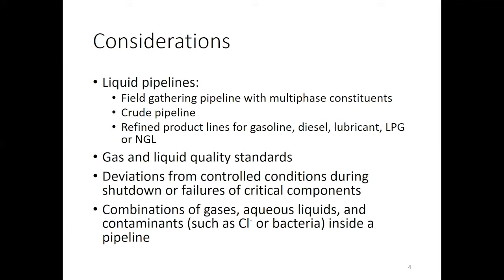For the gas or liquid quality standards, there are standards that have to be followed. Some deviations from the controlled or operational conditions that have already been studied or determined could happen, so that they would change for sure the method, or should change for sure the protocol applied for controlling corrosion, especially during shutdowns or unexpected failures or problems. Also, some combinations of gases, aqueous liquids, or contaminants such as chloride or bacteria in pipelines could change the method decided on for mitigating corrosion, as well as pipeline specific critical locations where corrosion could expectedly be high.